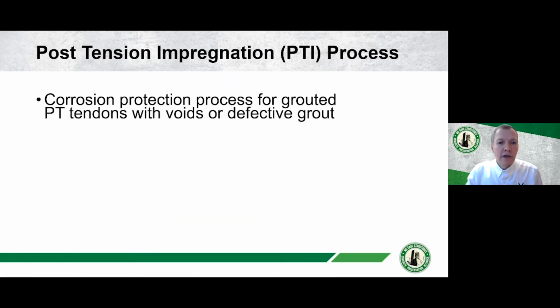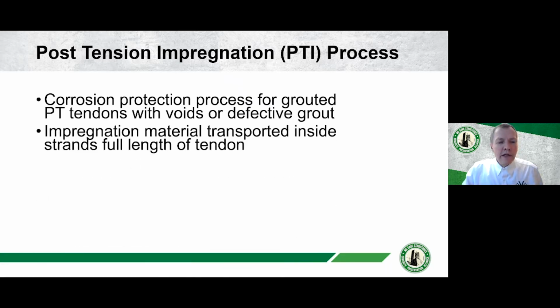And this is a corrosion protection process for grouted post-tension tendons. And generally these are tendons which have either voids or some type of defective grout. It could be used to provide additional protection to tendons without those deficiencies, but generally this has been used on tendons that have been identified that have these deficiencies. The impregnation material is transported inside the strands, and it's transported and treats the full length of the tendon. And I'll explain in a couple of slides exactly how that's done.